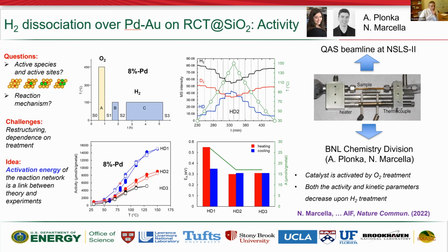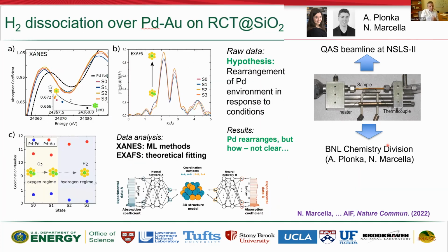And so after oxygen treatment, the catalyst had a very strong change, because initially it had very high activation energy and then it dropped, and you can see it from the data. And so the activity and kinetic parameters decreased on hydrogen treatment, and we wanted to understand partially why, not only what the reaction mechanism is, but what is the role of the structure of palladium for this deactivation.